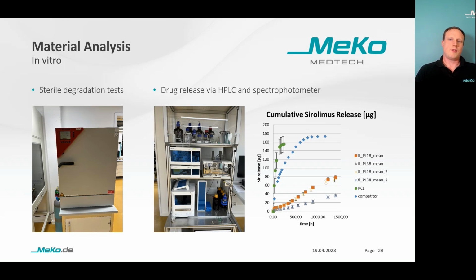Another very important topic is the drug release of drug-coated scaffolds. The drug release we can detect here in-house using high-performance liquid chromatography and photometry. And as you can see on the very right side in this graph, depending on the alloy, coating, and passivation, there are different release kinetics observable. So we tested several magnesium scaffolds with different coatings, and as you can see, the release kinetics are different depending on what coating you apply.